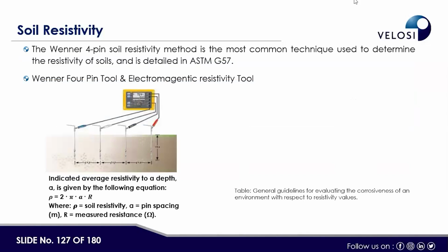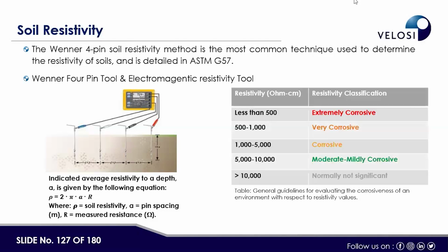So how can we measure whether your anode can work in this environment, and what would be your transformer rectifier unit capacity, what potential, what voltage, what current you need? For that we should have the soil resistivity. Soil resistivity gives you an indication of how corrosive the soil is. In the desert, sand is a very high resistive environment and less corrosive, whereas near the coastal area it has very low resistivity, highly conductive and highly corrosive. So resistivity and corrosivity are inversely proportional to each other. The higher the resistivity, like in the sand dunes of the desert, the lower the corrosivity, which means you need less current to fight it.